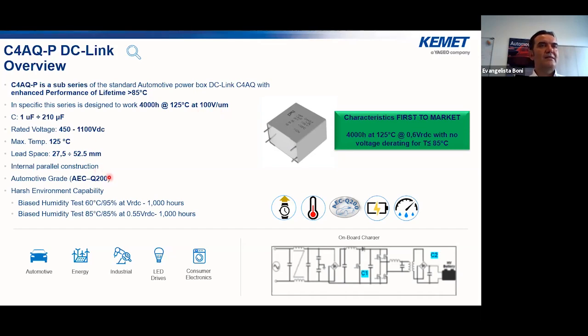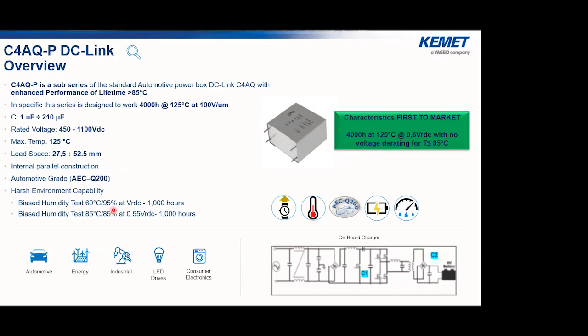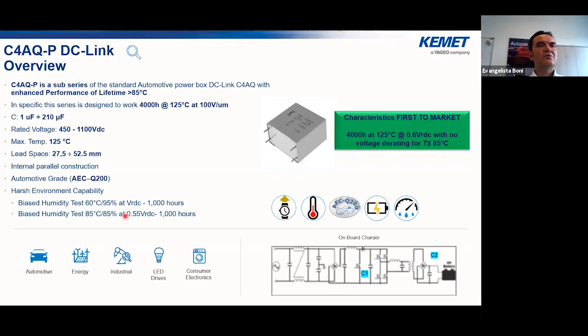It's AEC-Q200. It has a humidity capability of 60-95, 1,000 hours, but also 85-85 at not rated voltage, 0.55, for 1,000 hours. The main technology drivers for this capacitor are lifetime, temperature, AEC-Q200, power density, and also harsh environment. And this is one main circuit where this series can be used. It is a typical circuit of an onboard charger, for instance.